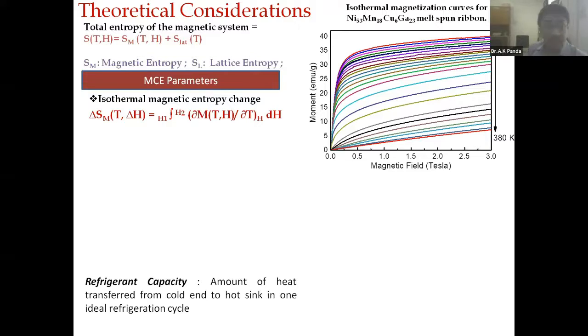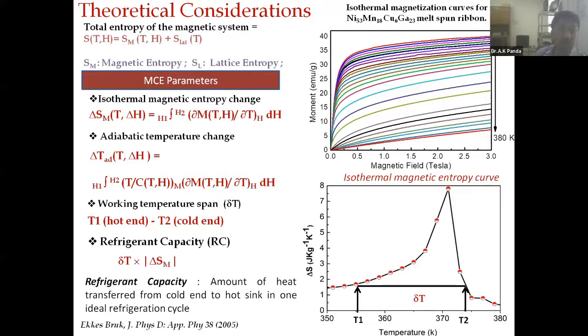On the left side, you see some of the magnetocaloric parameters, delta SM, when you play around with two magnetic fields, H1 and H2. This is the equation for the isothermal magnetic entropy change. As I told earlier, this is the adiabatic temperature change, which you desire to measure directly, but it is not that easy. In addition to these two parameters, there are two more. One is the working temperature span, from the hot end to the cold end. This is the span in which you want your device to work, and that is a very important parameter. When you judge the efficiency of the material, it is not only the high entropy that is required, but also the range of temperature over which you are able to work.